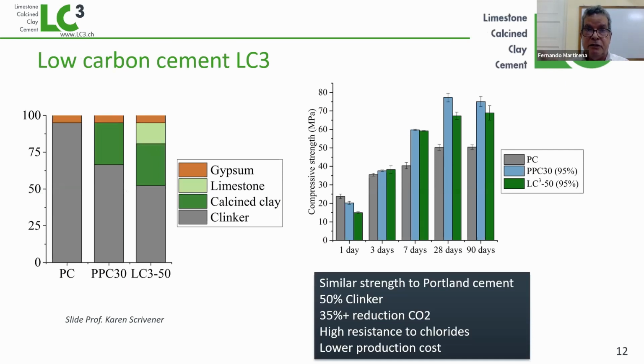This is the material we've been developing in the last 10 years together with this international team. You see here on the left side of your screen, we have pure Portland cement, Portland pozzolan cement, and then LC3. The interesting thing about LC3 is that you have only 50% of clinker, a higher amount of limestone, 15% limestone, and the same amount of pozzolan used in pozzolan cement, so 30% pozzolan, and you are able to achieve the same strength as a pure Portland cement at all ages. And that's the most important thing. You're increasing clinker substitution further, but you're retaining the strength of the material.